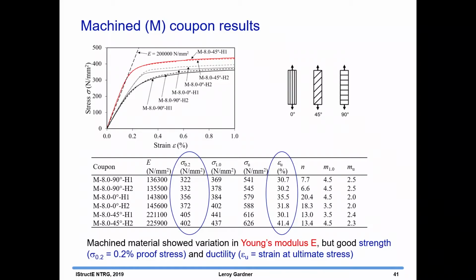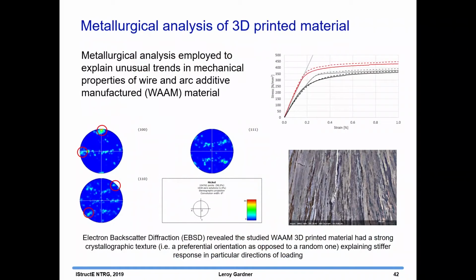So why did we have this variability in Young's modulus in particular? We went to speak to our friends in the materials department, and they said that you can investigate this using a method called electron backscatter diffraction. You can look at the microstructure of the material, and what we found is that the grains were preferentially orientated following the heat path that is generated in the 3D printing process, and that was able to explain the stiffer response in that 45 degree direction.